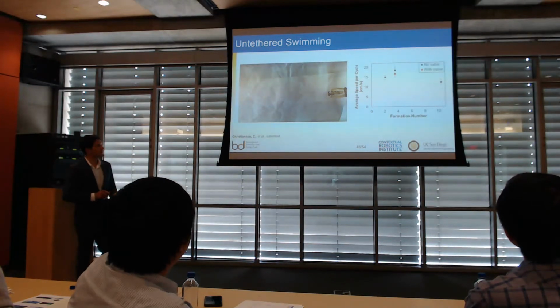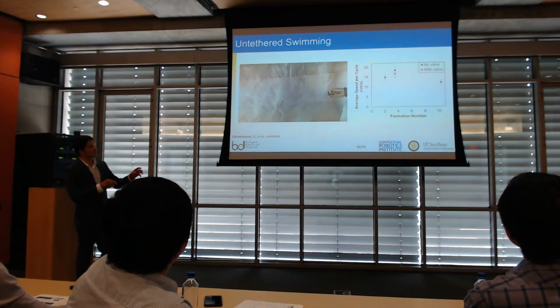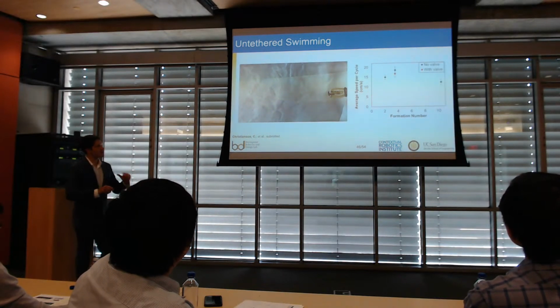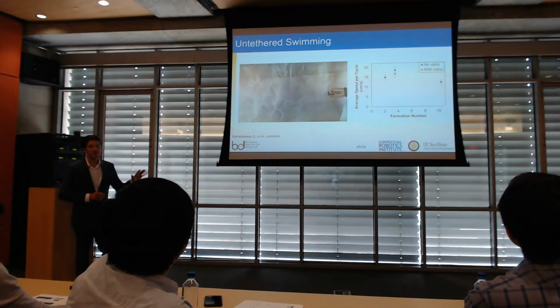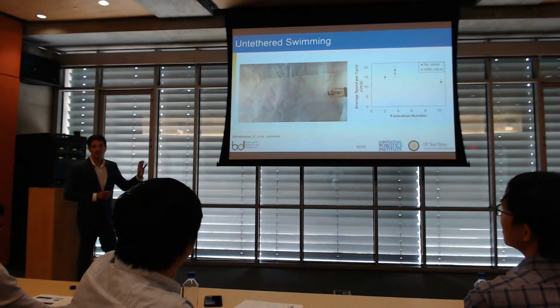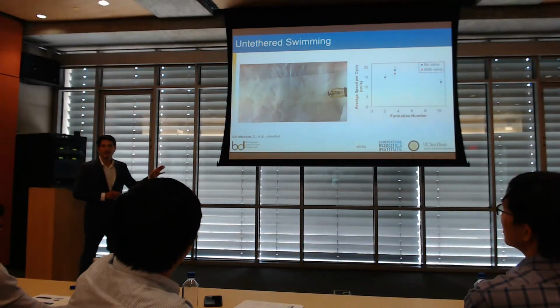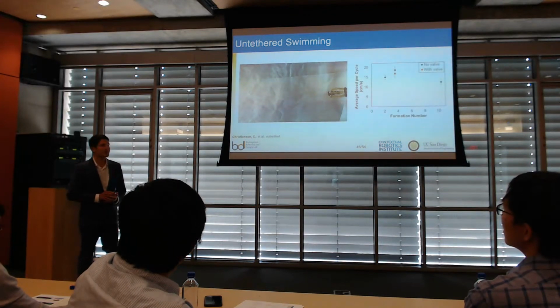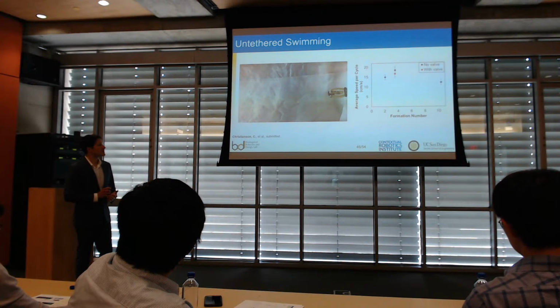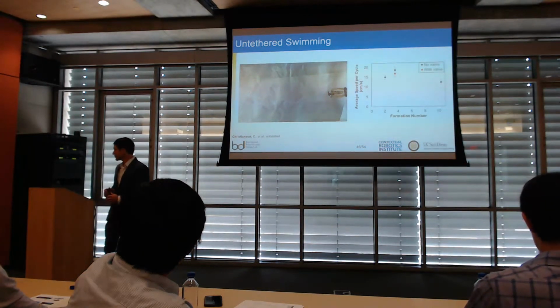And so you can see here there's kind of a trend where at low formation numbers, it's slower. At high formation numbers, it's slower. And then when formation number is close to 4, we get the maximum speed measured. And then the passive valve that we designed here didn't really improve the performance, but we're still working on trying to improve it in future work. So that was untethered swimming.